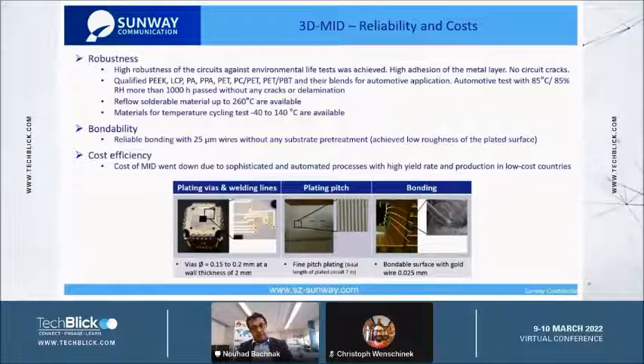We faced such issues, I would say, 6 years ago, and we have worked on a plating process where we have developed a specific plating process for plastic materials where we can withstand all the automotive tests, with more than 1,000 hours, especially the humidity and the temperature test. For industrial consumer goods, the requirement was 90% relative humidity at 65 degrees, 72 hours. And 6 years ago, we had one application where we faced some issues and started to develop this process. And we have achieved now more than 1,000 hours. Internal tests which were done were at 90 degrees and 90% relative humidity without any issues. Actually, after 500 hours, I would say the part has expanded enough, and nothing will happen. We have achieved 1,000 hours without any cracks, without any delamination.